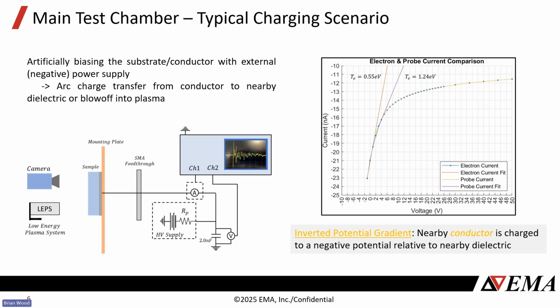It's basically just a soup of electrons and ions. Those will be attracted to the sample. They'll neutralize the top surface, and you can start to induce arcing that way. And this is a really controlled way of doing this test. And so you are controlling the bias. It's a really good way to slowly increase the bias and see when you start to see arcing, and determine the voltage threshold for arcing.